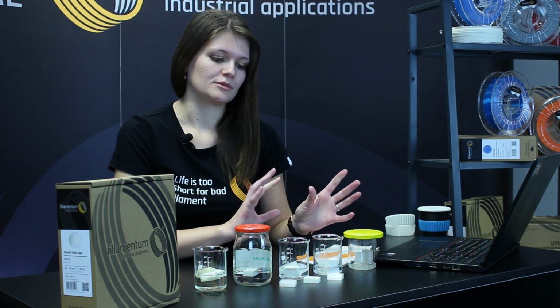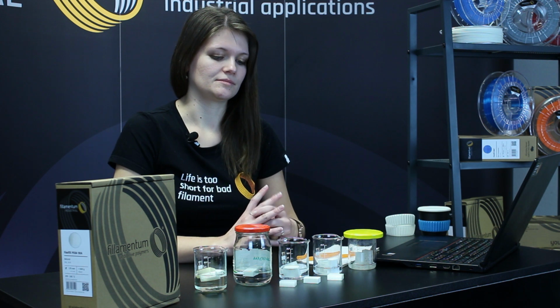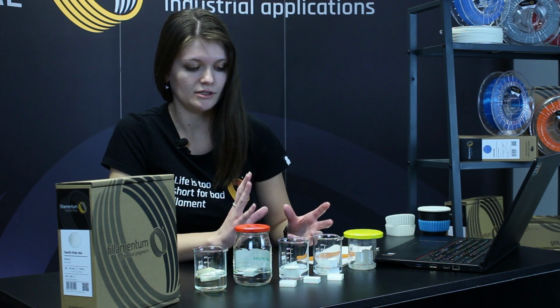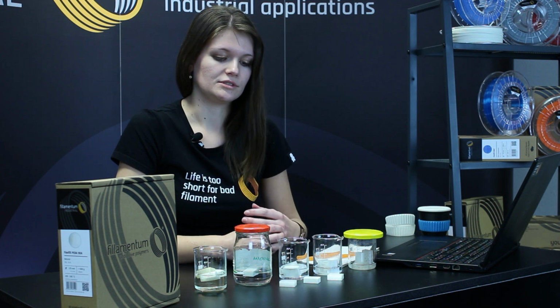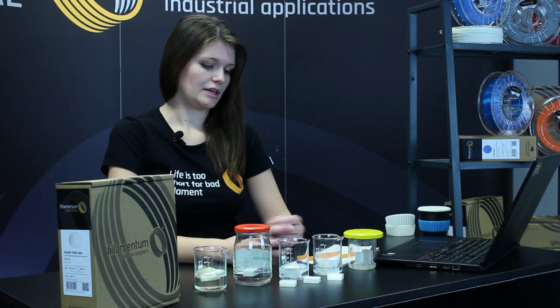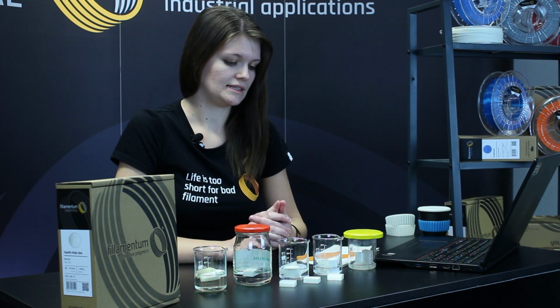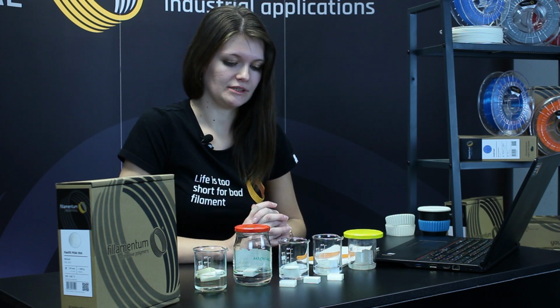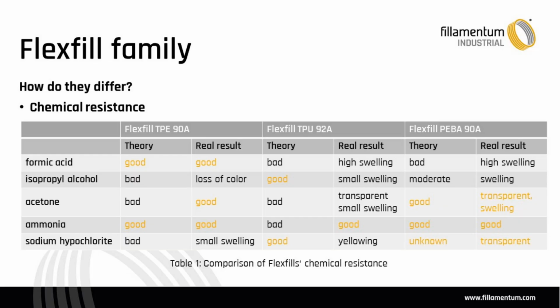We have prepared a few substances to achieve the swelling or a little bit of dissolving of the object, and we have put it into these substances for 4 days, and we can have a look at it and compare it. According to the theory, we have found that the resistance should be, for example, good or bad in case of formic acid and isopropyl alcohol, but